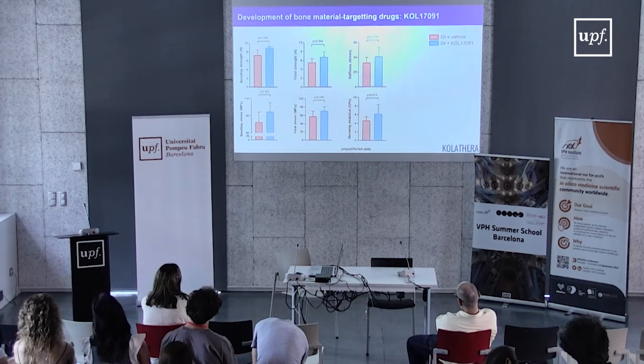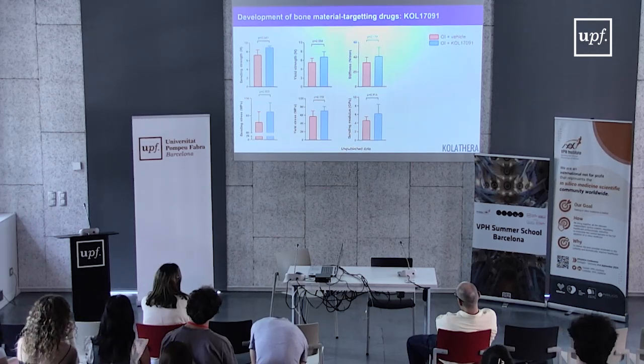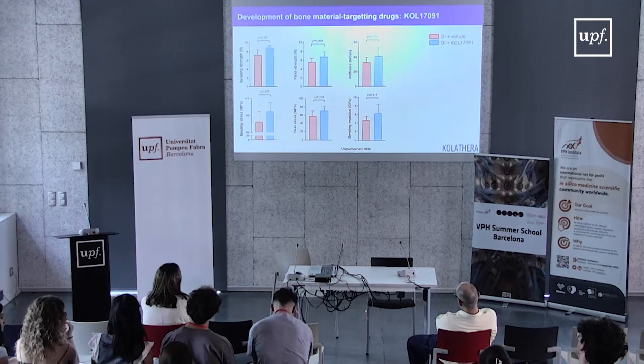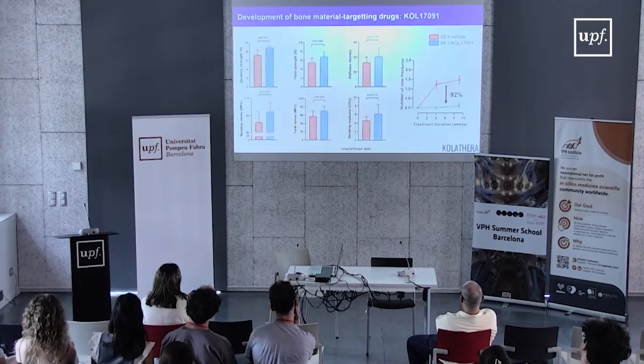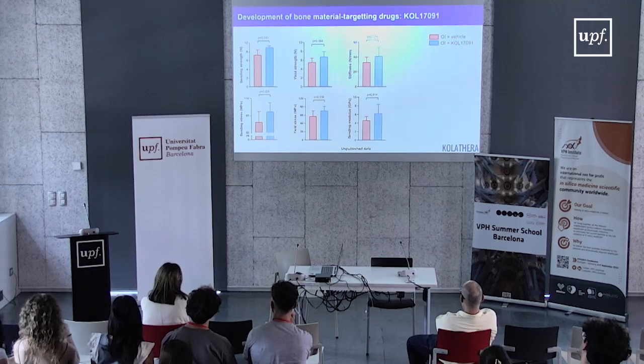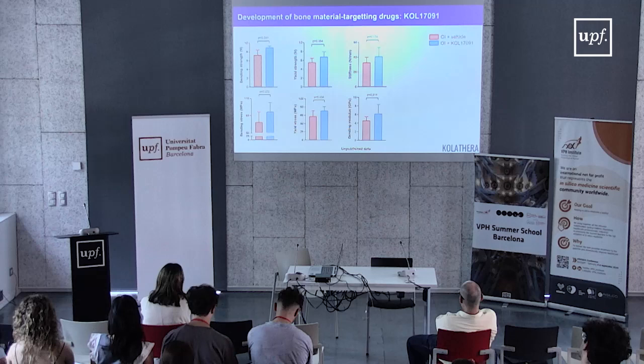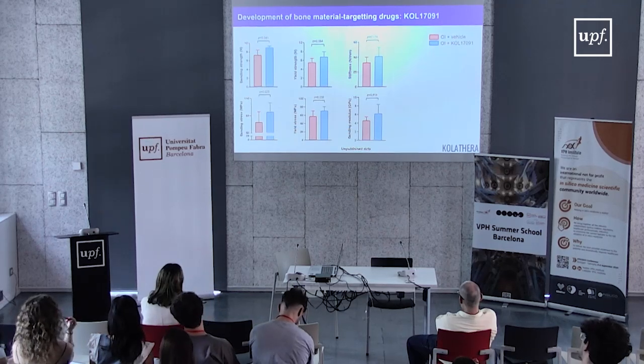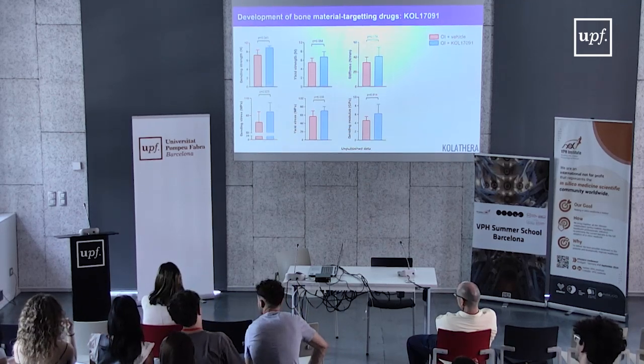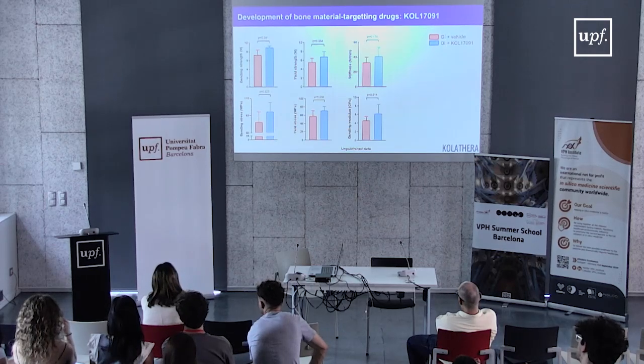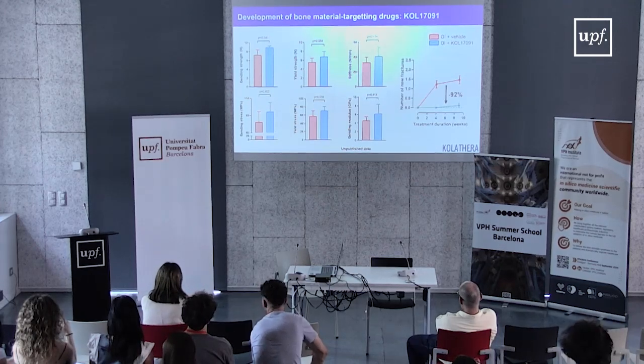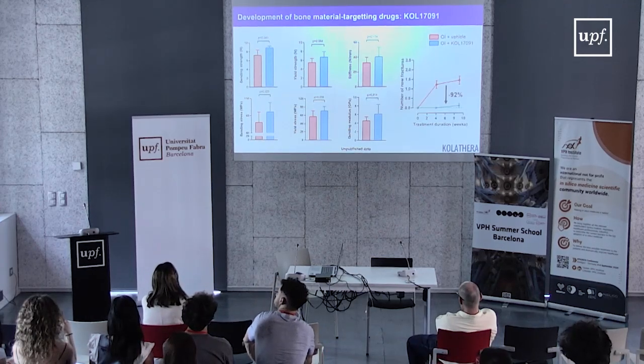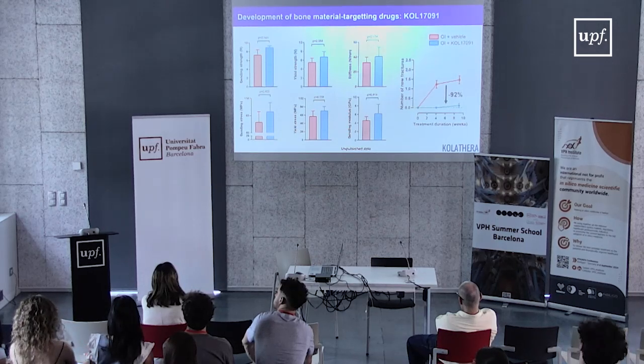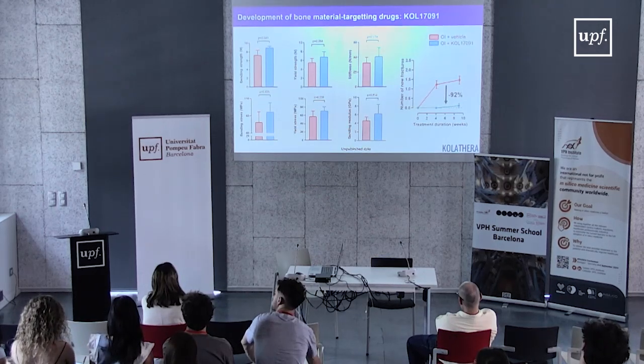And if we look at the bone strength of bones of OI animals treated with either a placebo or KOL, you can see that you increase almost every mechanical parameter. And more impressive is if we directly measure the number of fractures that these animals have, because these animals with OI have spontaneous fractures. Just by their daily activity in the cage, they can fracture their femur and humerus. And if we quantify the number of new fractures under treatment, by targeting the bone material properties, we can directly reduce by 92% the occurrence of new fractures.